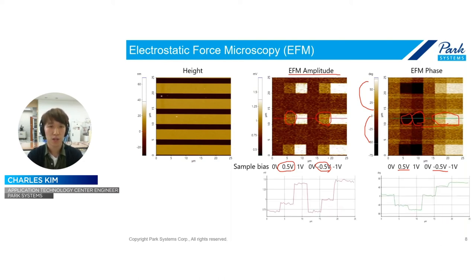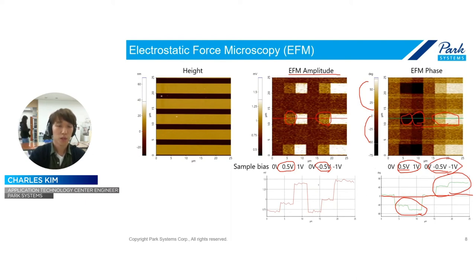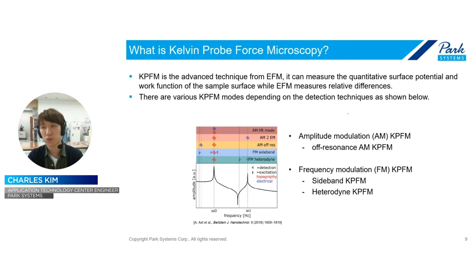And when I draw the line here, you can see the electrostatic force magnitude increasing depending on the sample bias, for 0, minus 0.5, minus 1. But the negative here means plus sample bias, and the positive means minus sample bias. This is the EFM. But there's one question: even though I apply 0.5 here, the EFM amplitude is only under 1 millivolt. This is not the real value of the potential, but we want to know it. So for that, we need to use the Kelvin probe force microscope.